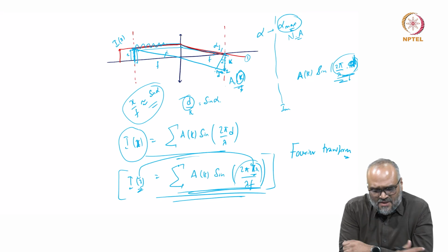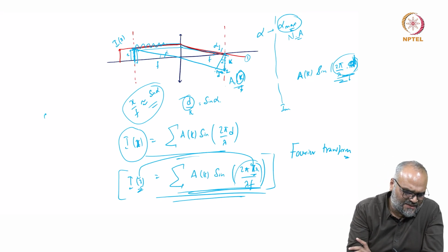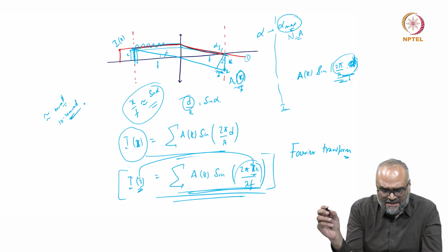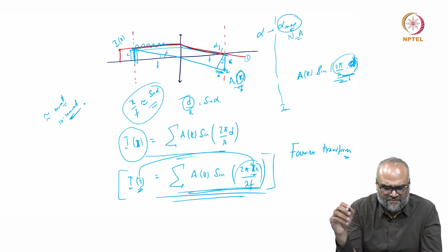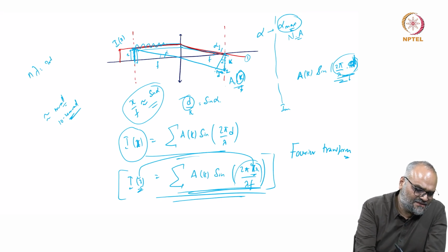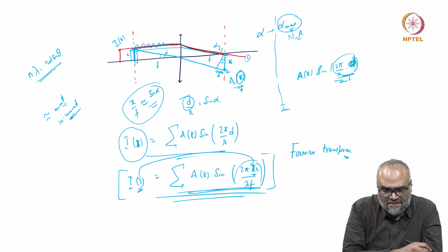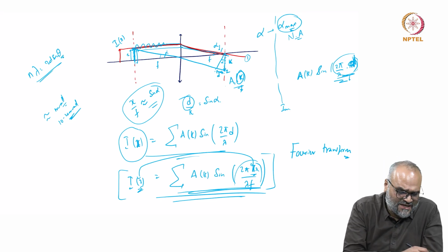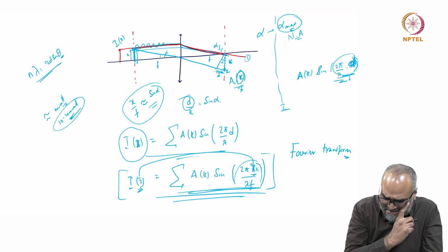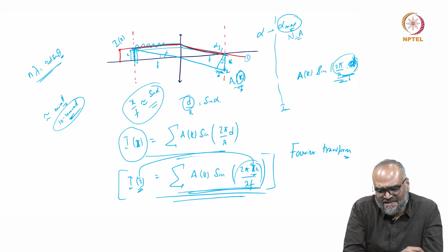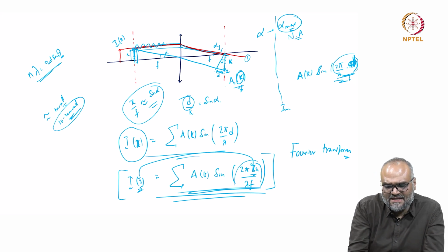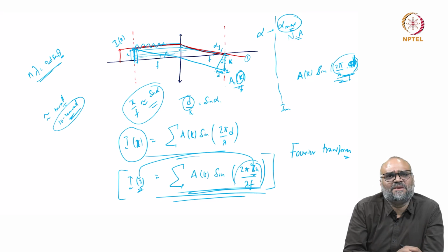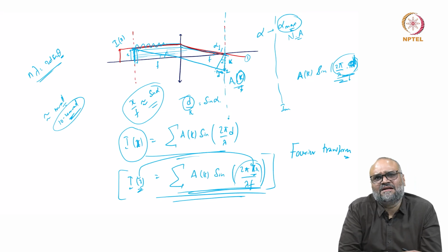In an electron microscope, when these angles of deviation are extremely small, typically of the order of a few milliradians, say typically 10 to 20 milliradians, and if you apply Bragg's law here, which says n lambda is 2d sine theta, for very small angles theta, of the order of 10 to 20 milliradians, all my planes within a specimen which are satisfying Bragg's law are nearly paraxial and parallel to the optic axis, and all these would now converge and form some kind of a periodic pattern at the back focal plane.